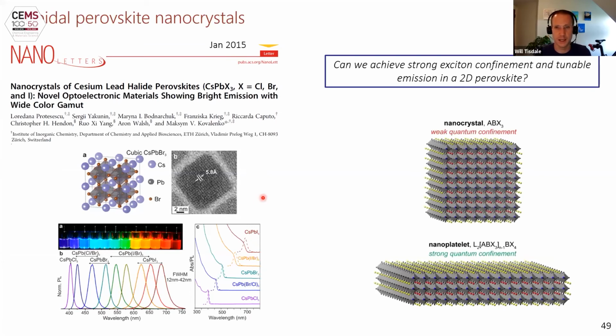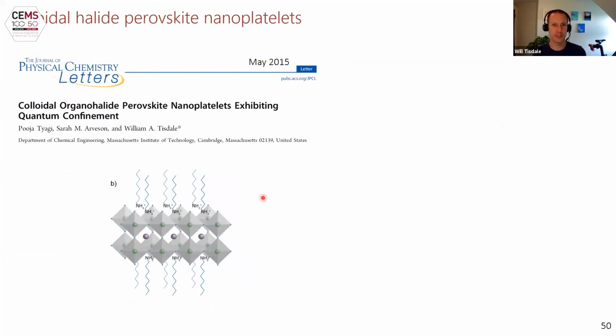What if we could make an atomically thin 2-dimensional version of a perovskite nanocrystal? Perhaps then that 1-dimensional quantum confinement could be more extreme than the weak confinement in 3 dimensions. The first time we did this was completely by accident. We synthesized nanoplatelets or atomically thin sheets of methylammonium lead bromide coated with butylamine ligands in solution. It was a byproduct of another synthesis we were trying that we correctly isolated and identified.